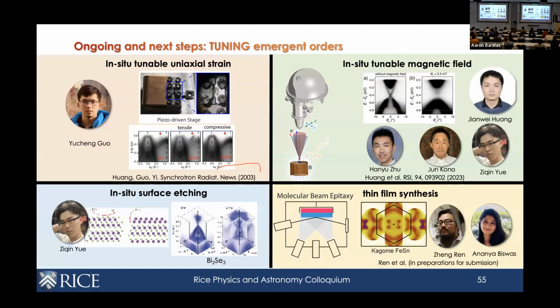And in terms of instrumentation design, we're also very interested in exploring different ways that we can do in situ tuning. So here are four. This is a uniaxial strain we can apply in situ. We can compress or drag the systems and directly measure ARPES and see the changes in band structure directly. This is the in situ surface etching. So this is bismuth selenide, which is a topological insulator. By reacting chemically on the surface, we can see very nice evolution of topological surface states.